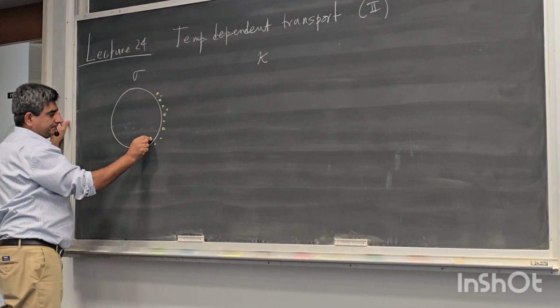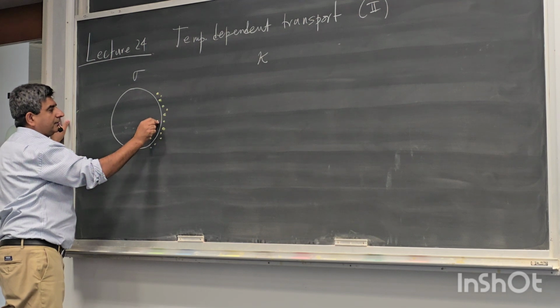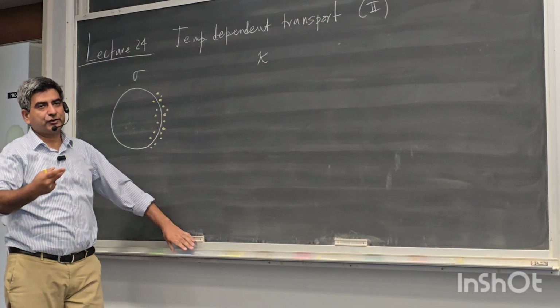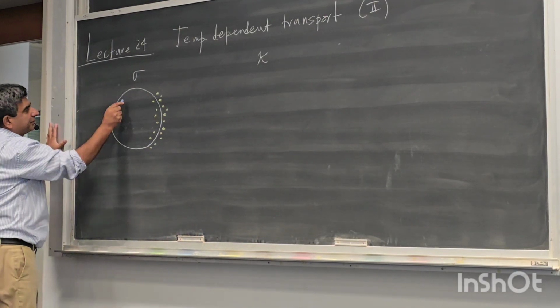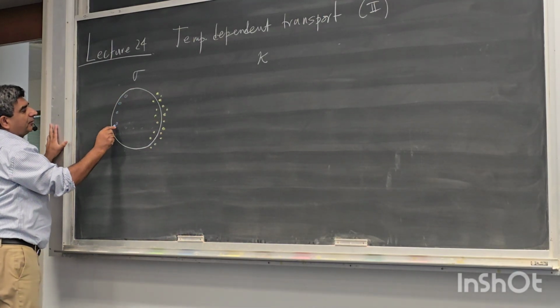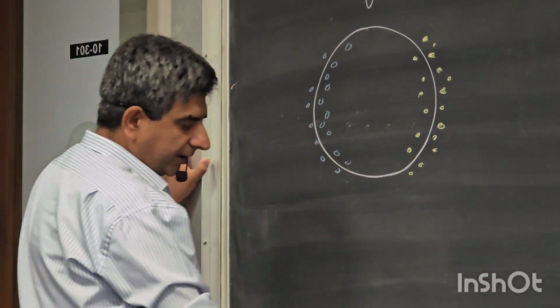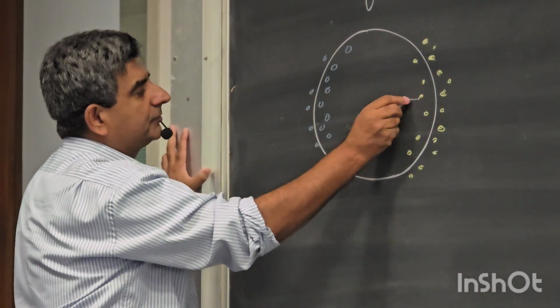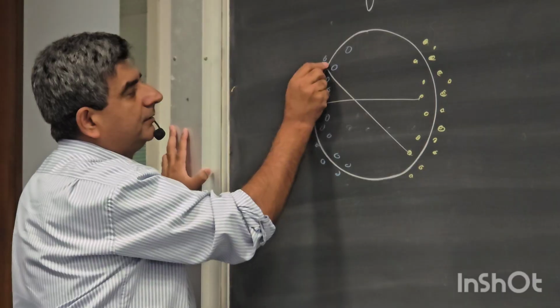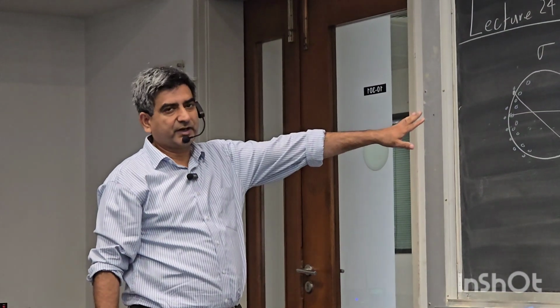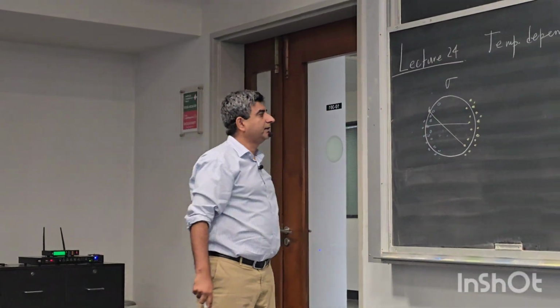comprised of momentum transferal kicks, that is horizontal processes in which these electrons on the right side of the Fermi sphere can be catapulted into the holes on the left side of the Fermi sphere. So this is the most efficient mechanism for thermal conductivity, electrical conductivity. And